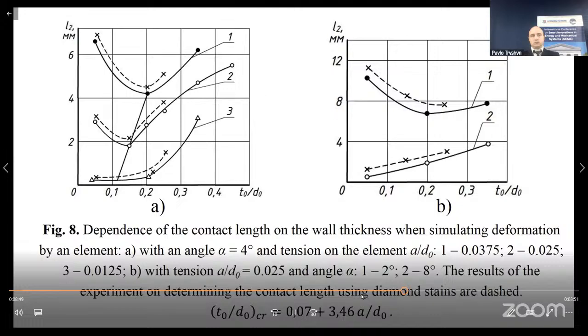Figure 8a shows a change in contact length as a function of workpiece thickness when using different tensions. It follows from figure 8 that with an increase in the thickness of the workpiece, the contact length first decreases and then begins to increase, with a clear bend in the function in the region of the critical wall thickness. It is clearly seen that the value of the critical wall thickness depends on the tension on the element and the angle